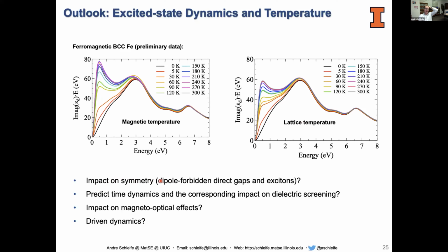So we trace this back to breaking the symmetry essentially, making an otherwise dipole forbidden transition dipole allowed, weak but dipole allowed, and that leads to these changes here, both for phonons and for magnons. But I think the impact and the implications are broader than just that. I think this could affect excitons and things like that. We just started looking at that.